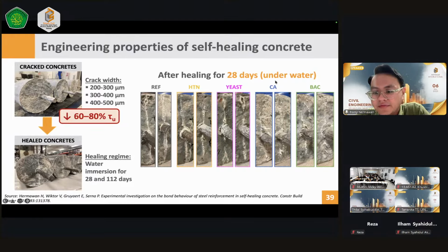In particular, if you look at the crystal admixture, CA and also BaC, you will see there was a formation of what we call stalactites. So there was a formation of stalactites as minerals forming on the crack mouth, and this is due to the formation of the minerals from the inside protruding to the outside. Okay, so there was a very strong healing activity with the use of CA and BaC.